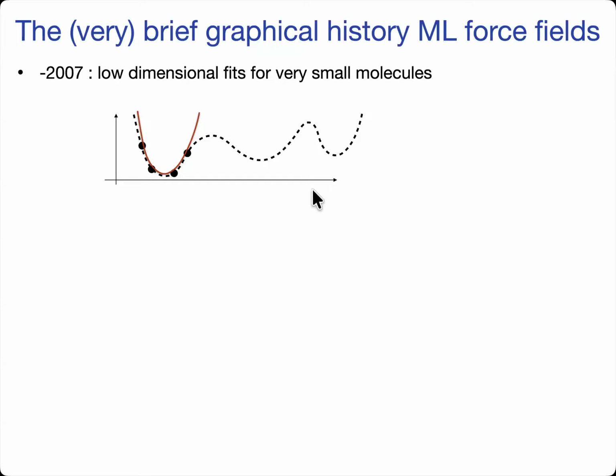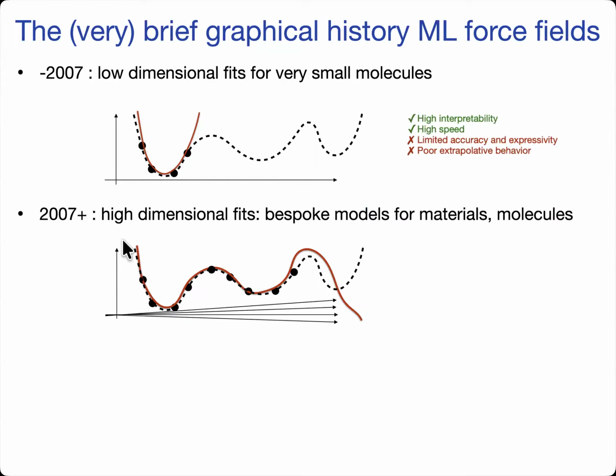So before 2007, before the seminal work of Behler and Parrinello, of course, people had used ML-type techniques, neural networks, to fit potentials, but only very low dimensional fits were made for very small molecules. And of course, you really understand what's going on. You have 2 or 3 dimensions and you fit a function, but that doesn't really give rise to new kinds of simulations. Beginning in 2007 is this sort of 10, 12 years of iterative fitting, and the idea that with good descriptors, you can make bespoke models for given materials. And if you have data everywhere, then you can interpolate that data, and where you don't have data, the models were rubbish. So very poor extrapolation behavior, but locally very accurate.